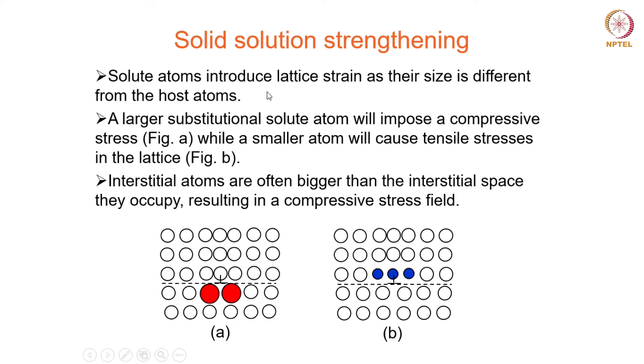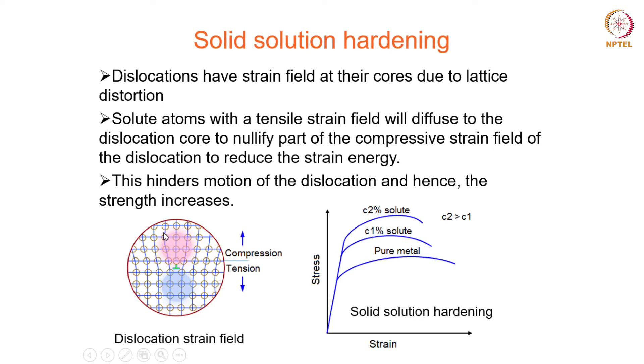In either case, this causes some kind of lattice strain, and this is what is responsible for the impediment to dislocation motion. To understand why this stress field restricts dislocation motion, we need to look at the dislocation and the stress field around it. The dislocation also has a stress field because it is a distorted portion of the lattice. Across the dislocation — above the half plane there is compression, and below it there is tension.